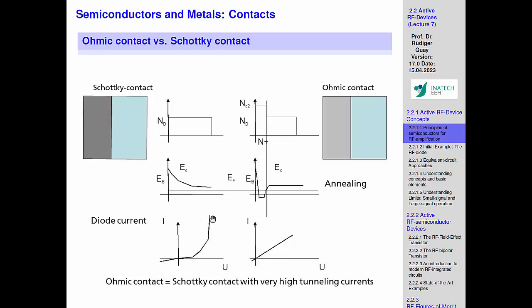And when you then measure the current for the diode, you get a typical diode behavior here. But if you dope it to get the carriers very near the interface, you really measure an ideal ohmic contact. And the higher you dope, the lower the resistance actually is. So that's quite simple. That's what we need there.